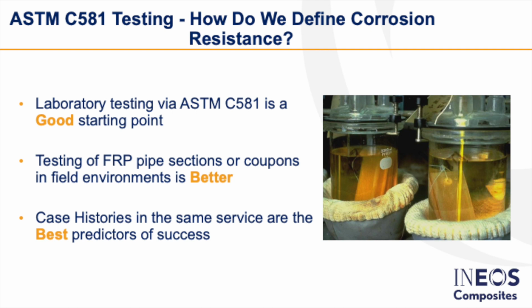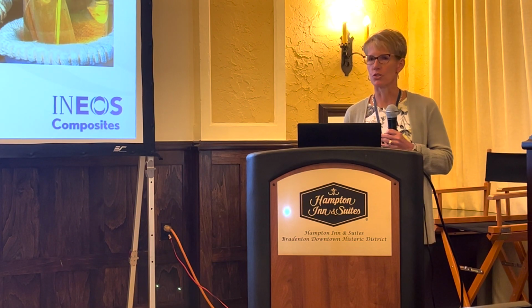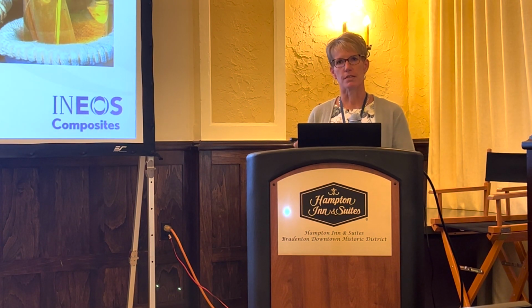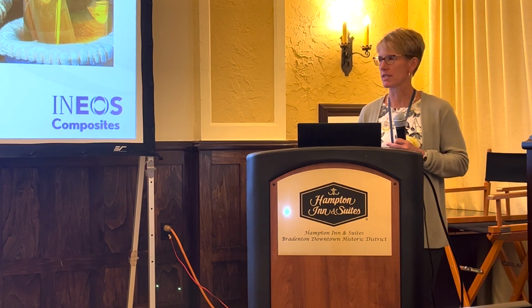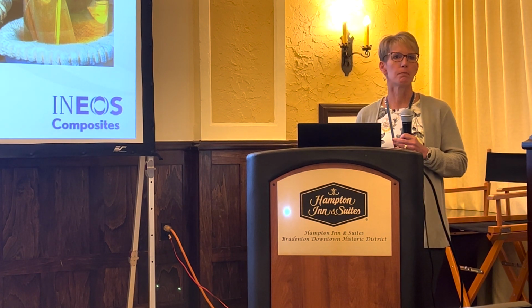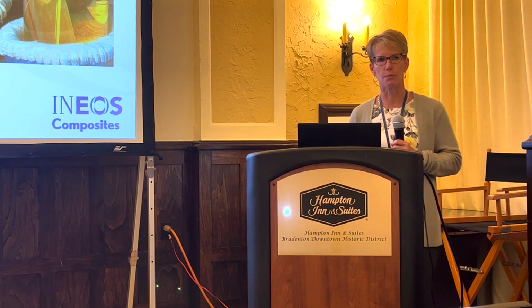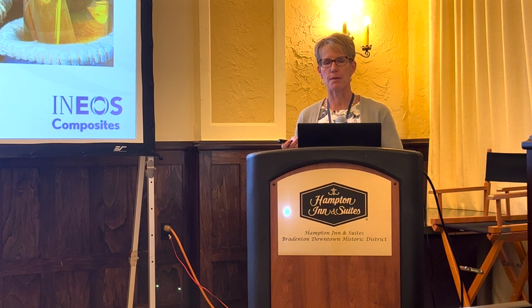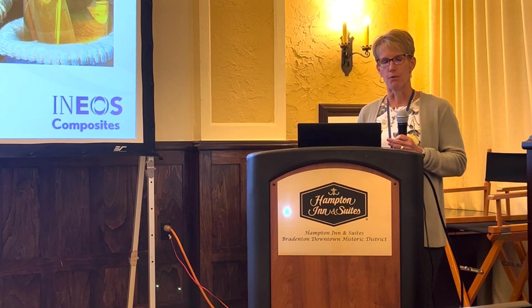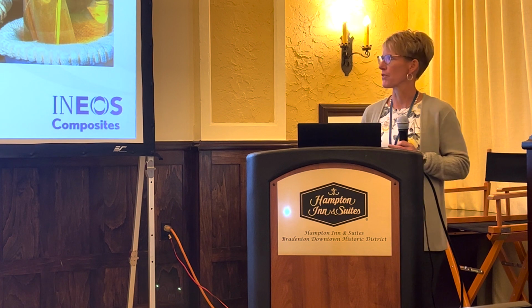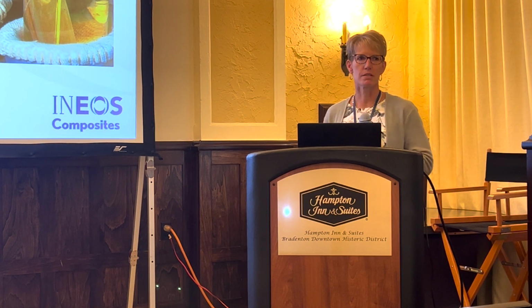When we do laboratory testing per the ASTM C581, it gives us a good starting point for determining which resin is going to be suitable for which environment. But then an even better option is if we can submerge pipe sections or coupons, give those to the customer, and they can put them in the actual environment at their facility. After a period of time, whether it's 6 months or a year, they can send those samples back to us, and we can evaluate those in the laboratory and determine whether or not that resin is good for that specific environment. So that's an even better way of determining what resins are suitable.